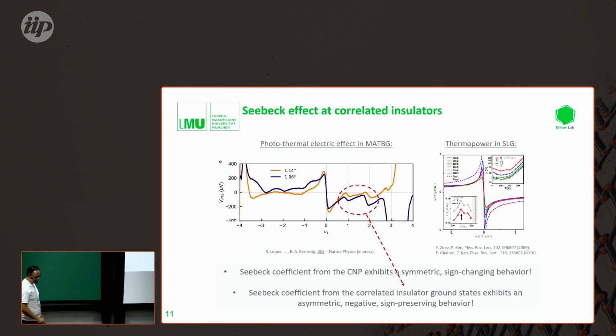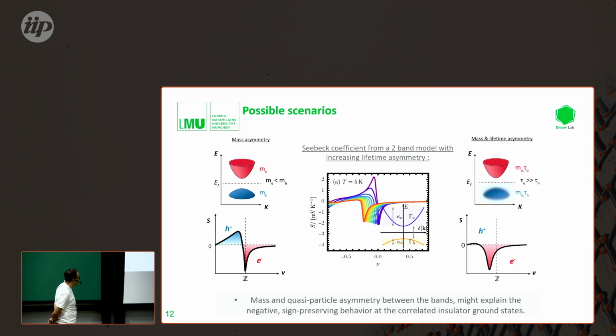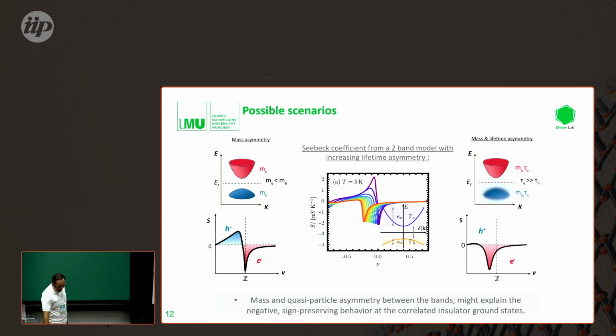so basically we see this sort of different switching behavior or a Seebeck effect at the integer fillings, and we were just trying to understand, sort of motivated by the theory, what could be the ingredients that can give rise to something like that. And we had just assumed, okay, so what happens if we have an electron-hole asymmetry in the mass? So if one band is heavy, the other one is light, can we get some sort of behavior like this? And it turns out that we do get an asymmetry between hole and electron Seebeck effect, but we do not get a complete suppression of one of the sides here.